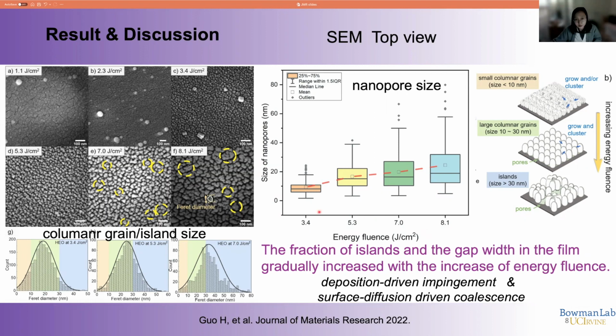There are two principles or mechanisms that can explain this phenomenon. One is deposition-driven impingement. The other is surface diffusion-driven coalescence. During increasing the energy fluence, that means the deposition rate of the films also increases. So the columnar grains will grow faster than in the low energy fluence.